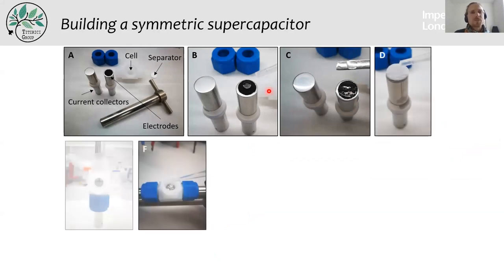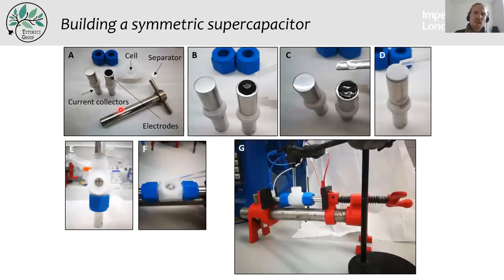In our lab, when we build our supercapacitor, you can see here we have two stainless steel rods that are anti-corrosion steel, and we put our electrodes like this. There is no substrate, no foil. That's why it's called a freestanding electrode. Then we add the electrolyte, we soak it, we add here the glass fiber separator, and then we press the whole thing. We connect the counter electrode, the blue cable, to one terminal, the working electrode, the red cable, to the other terminal, and we have here a reference electrode that allows us to monitor both potentials independently.